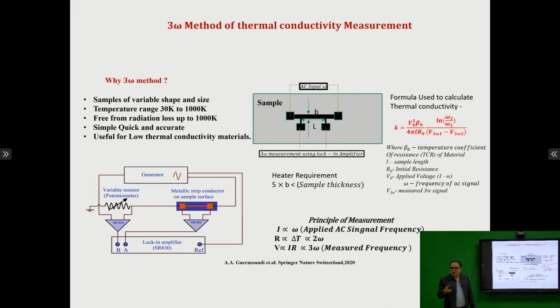Why is it called that? Because when you give current to this system, it starts heating. If you give power to the line heater, you will find a thermal fluctuation, and due to that you get a voltage drop, which is actually the third harmonic. You are giving an AC of frequency omega, and you get a voltage from the thermal conductivity part at 3 omega, which is the V3 omega.